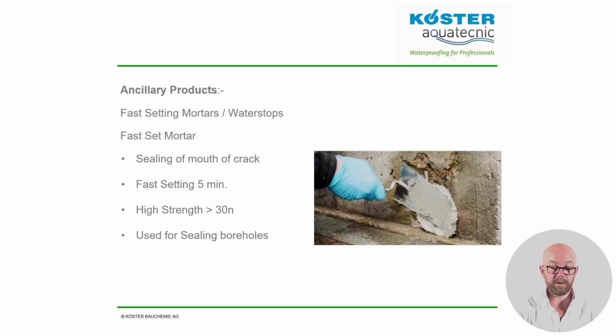Why do we seal the front of the crack if it's dry though? To keep the injection resin in the wall during injection. Because when you start injecting, the resin's under pressure. To equalise that pressure, the resin looks for the fastest and easiest route out. This will often be straight out the front of the crack and down the surface of the wall. But we want the resin to move slowly along the crack pathway and seal the whole depth of that crack. Therefore, we use the mortar to seal off this escape route. The same mortar is then also used after removal of the injection packers to seal up those boreholes.